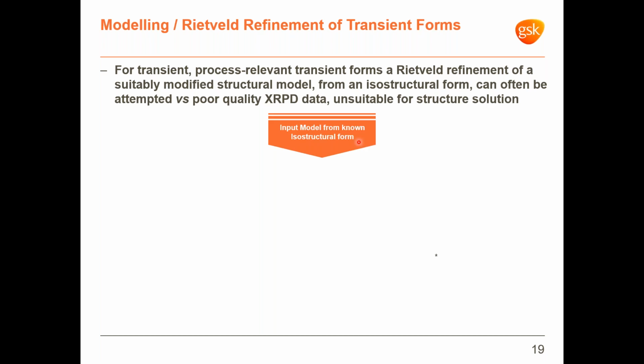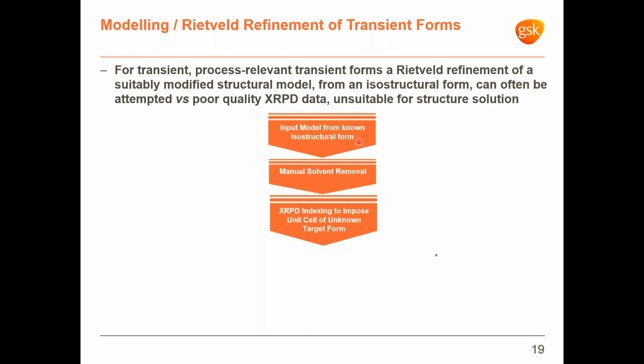Given the transient nature of the target form, we must rely in this case on the availability of an isostructural model from either the final development form of the dried API or from an isostructural solvate as a prerequisite. Once we have this, as a first step, we remove the solvent from the structural framework of the related form. Next, we transfer the dry structure in the unit cell of the target transient form, which we must have previously determined by XRPD indexing. XRPD indexing is, of course, assumed to confirm that the known and target forms are isostructural.